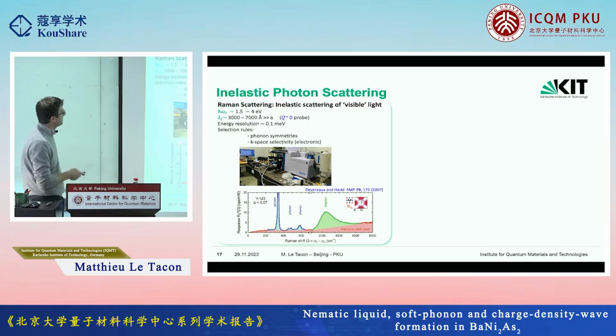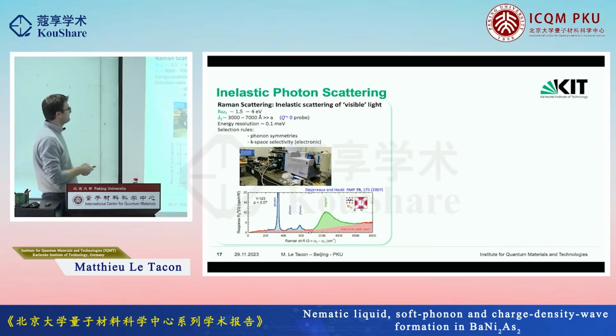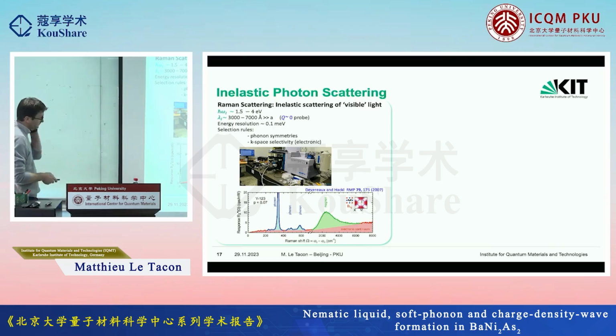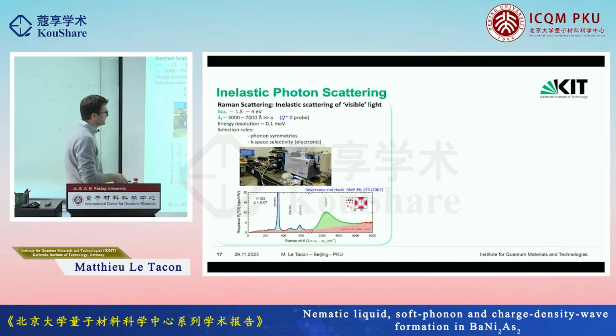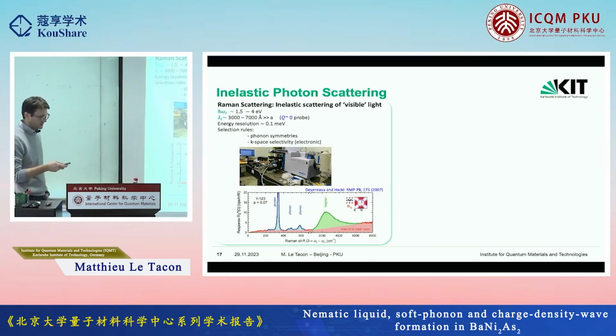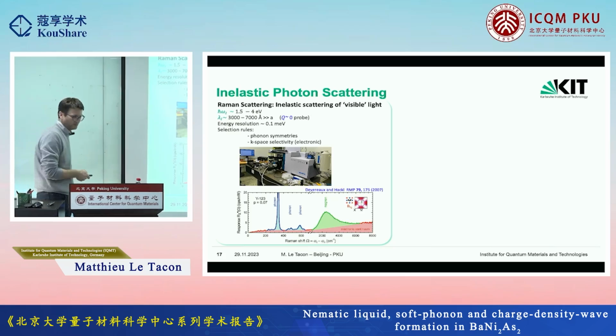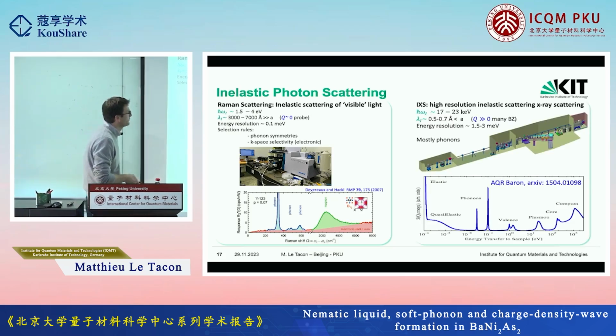Regime number one is that of visible light. So this is a setup which is very similar to that of Yuan here. It's a small Raman spectrometer where we work with incident energy of 1.5 to 4 electron volt. So this is a very long wavelength, so that's pretty much probing the excitation at the zone center of the system. But it has a very good energy resolution, typically less than 0.1 milli-electron volt. And with this, we are mostly going to look at phonons. But in principle, you can look at other kinds of excitation. Turns out that in this particular system, phonons are the main degrees of freedom I'm going to focus on.